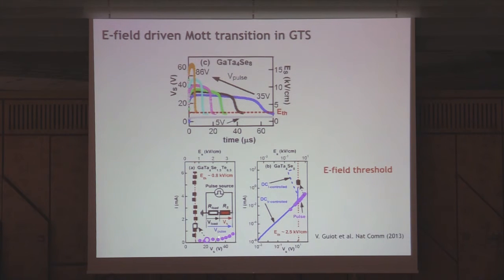So the change from this low current to high current is this transition from this high voltage to the low voltage on the sample. So this is the voltage on the sample. So you see that when there is a transition, the current shoots up, and the voltage becomes pretty much regulated. And so this is very fast. This is getting slower and slower, and here is the limit of very small voltage above the threshold field. So this takes longer and longer to get the transition. So this indicates a very well-defined threshold magnitude for the field, which is of the order of a kilovolt per centimeter.